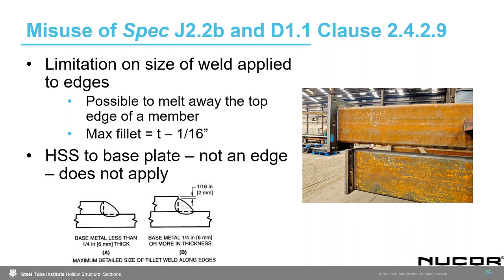So you would result in a normal weld toe, but the corresponding weld throat thickness is much smaller than what you intended if you melt away the top edge of that member. And so the provision states that the maximum fillet weld should be the thickness of the member minus 1/16 of an inch. The reason for that is so that you can confirm that the edge is not melted and the proper throat thickness is achieved.